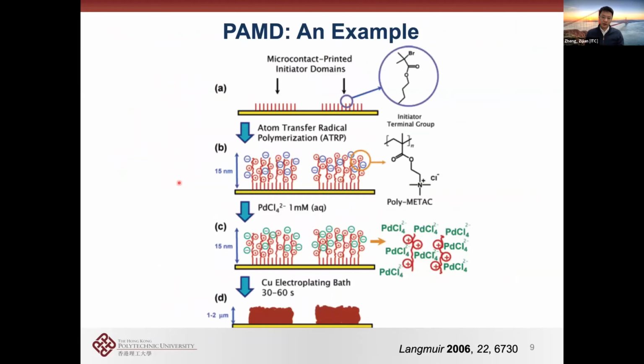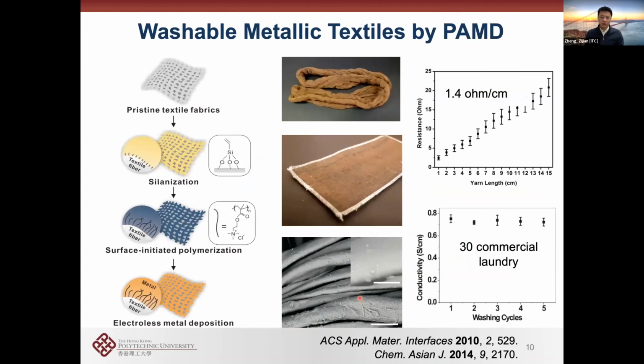So I'll give you a very specific example of the chemistry. So basically, this is how it looks. You can start to grow this polymer, and in this specific case, it's a cationic polymer, so nitrogen plus. This nitrogen plus allows you to absorb these anions, which allows you to deposit metals from the bottom up through an electroless deposition process. So this is very unique, and very easy to do in a room temperature environment.